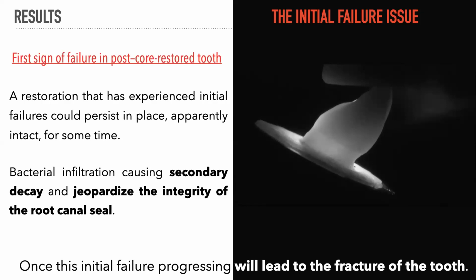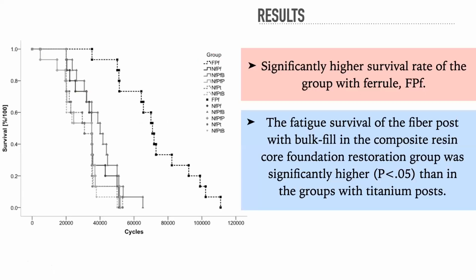So here we have the results of this study. You can see the life table survival, and we can see a very different line. This very different line is the ferrule groups. So we have a significantly higher survival rate for the group with ferrule, and the only group that presented a different result was the group with glass fiber post and bulk fill composite resin. Foundation restoration was significantly higher than in the group with titanium post.